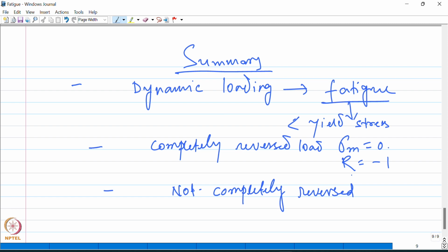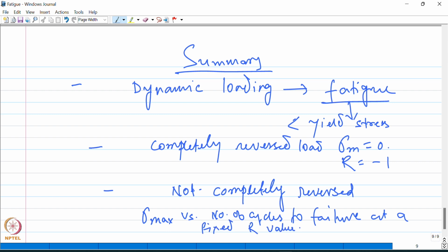So in such cases, we have seen that the fatigue data can be represented by plotting the stress, for example the maximum stress, versus the number of cycles to failure at a fixed R value. And in that case, R is kept constant by applying a series of stress cycles with decreasing maximum stress and adjusting the minimum stress such that it is a constant fraction of the maximum stress. So that's how R will be kept constant. And then it can be plotted against the number of cycles, and you can get a series of plots as you vary R.